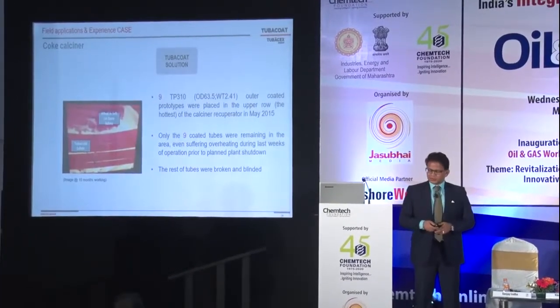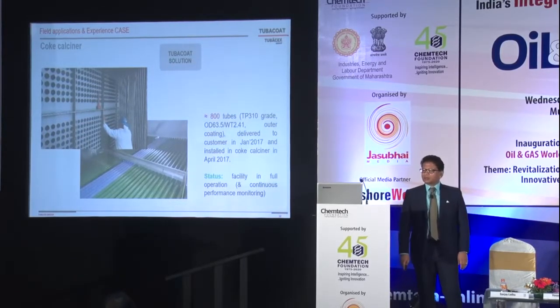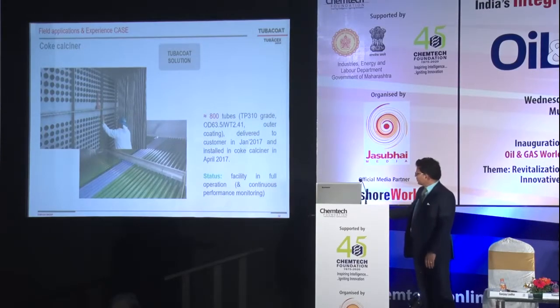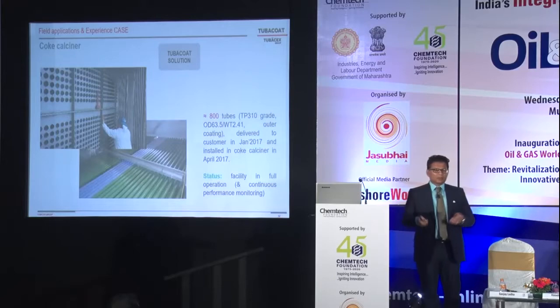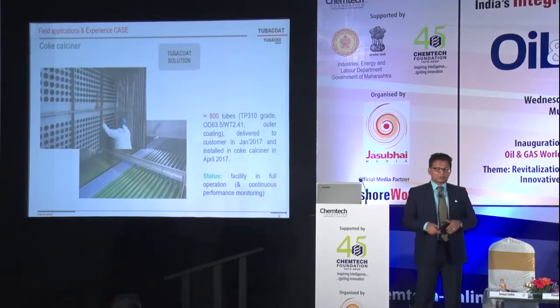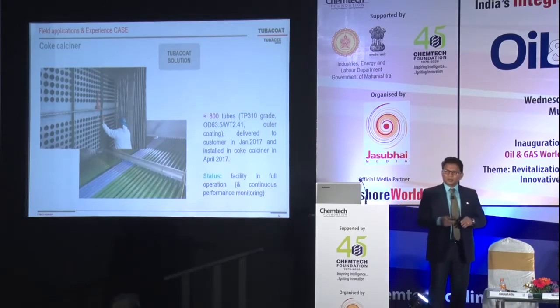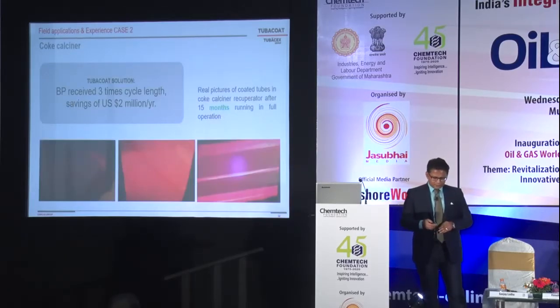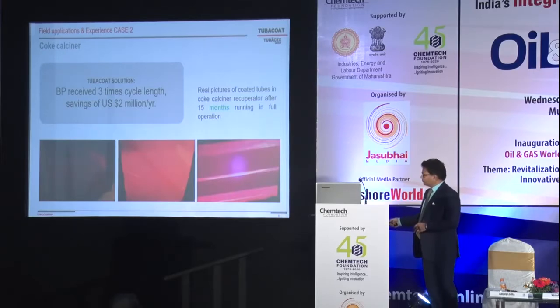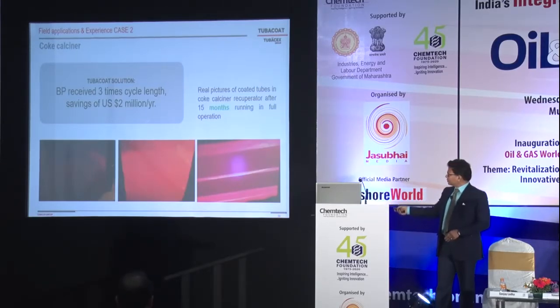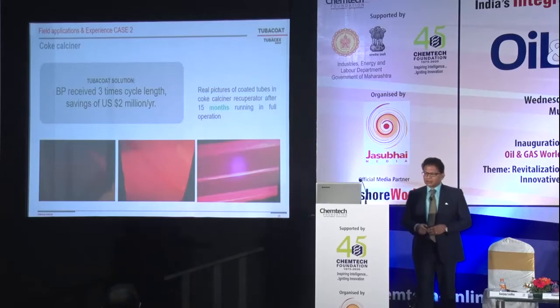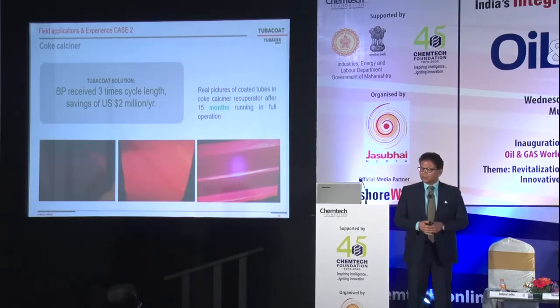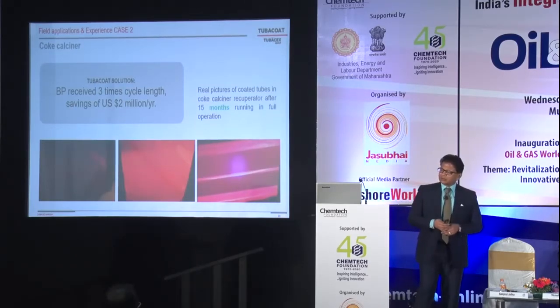BP liked the solution so much that they went for 800 fully coated tubes that you can see, and you see two different colors because we designed them for different temperatures depending on your application. We can go up to 850 degree skin temperature, or 700. We customize these coatings depending on what the problem is. So let's see the results. After install, when you look through a furnace window, you see an incredibly good temperature profile, no hot spots, no fouling, across the length of the whole radiation section. After 15 months, they are still intact. They got 3 times the cycle length, absolutely $2 million in savings, and now BP has become our strategic global customer for this technology.